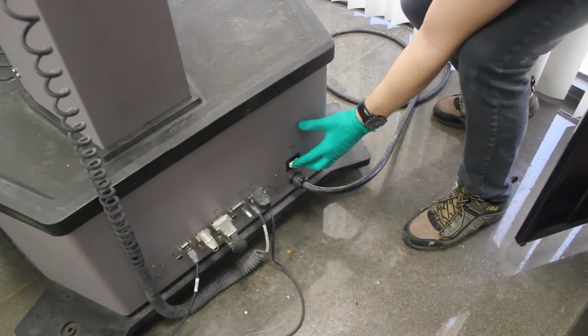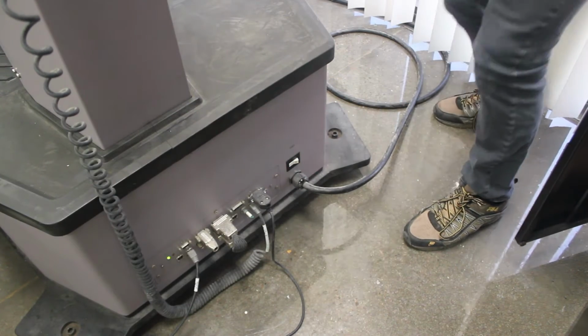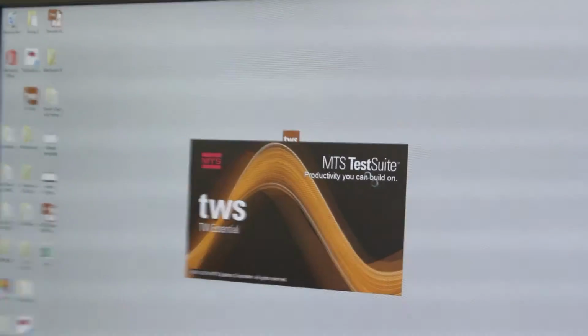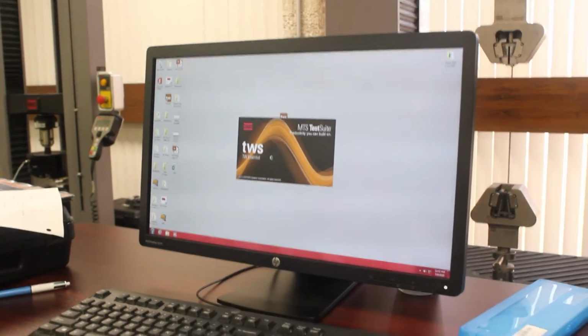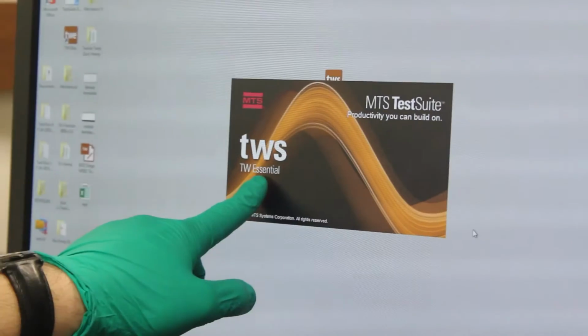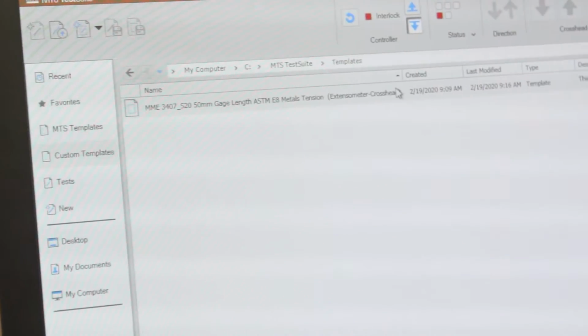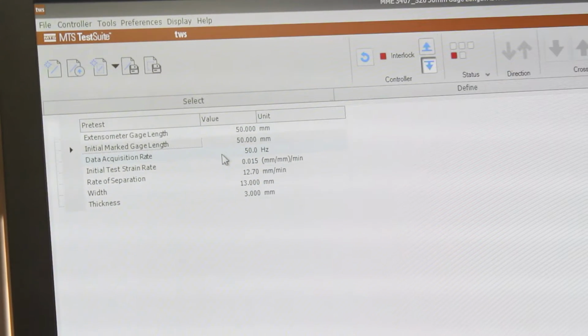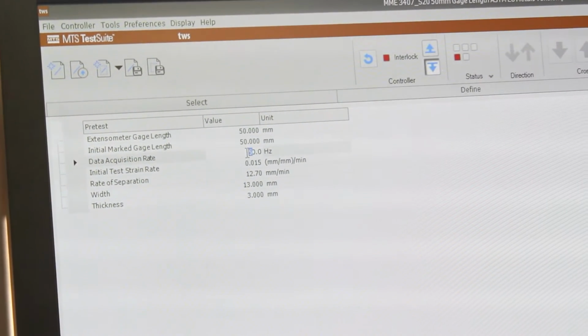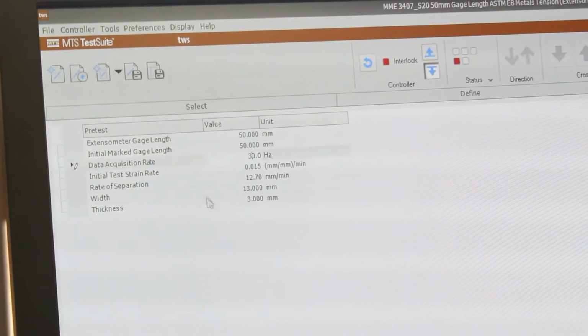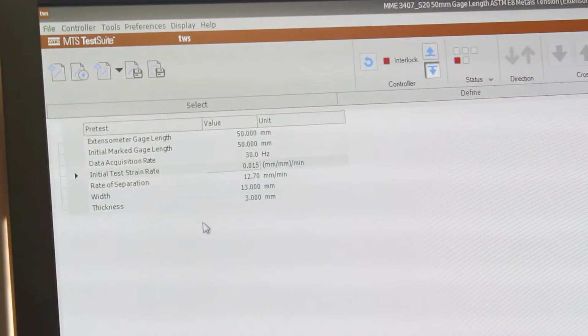First, turn the tensile tester on with the power switch located on the bottom right. Next, open the TWS Essential software, which you will use to control the tensile tester machine. Next, select the 3407 template from the Custom Templates tab. From the Testing Parameters page, lower the data acquisition rate to 30 Hz to make the test more efficient and lower the file size.